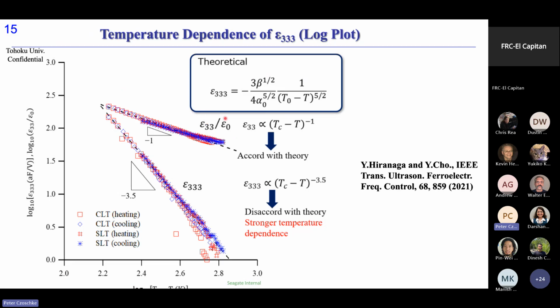This figure shows the principle of this new reading method. About 4 years ago, we measured the temperature characteristic of linear dielectric constant and non-linear dielectric constant of lithium tantalate crystal. Of course, linear dielectric constant obeys the Curie-Weiss law. It is inversely proportional to Tc minus T. Tc is the Curie temperature.